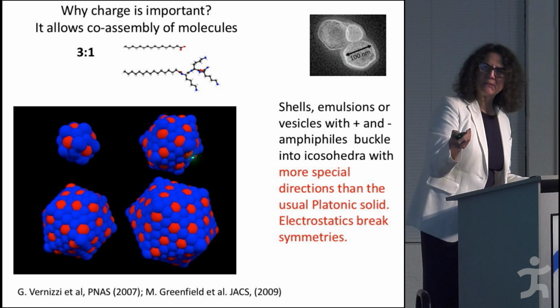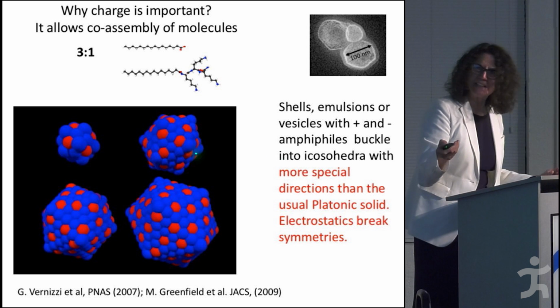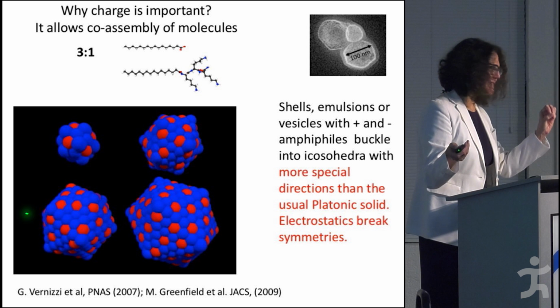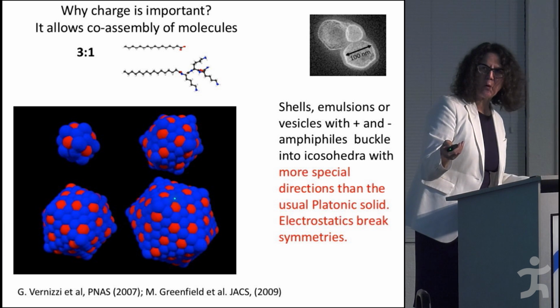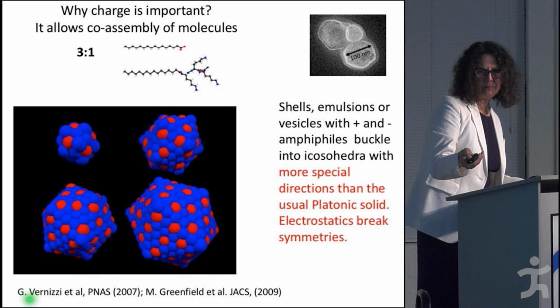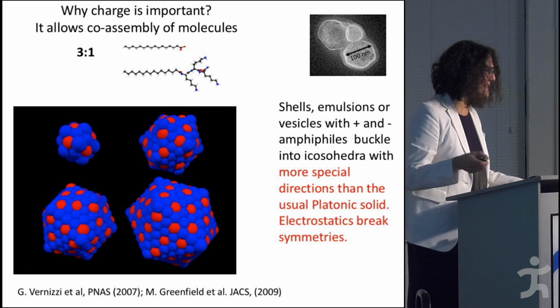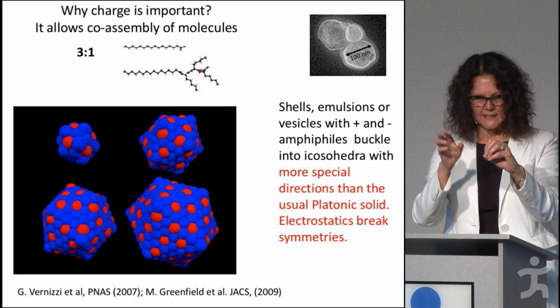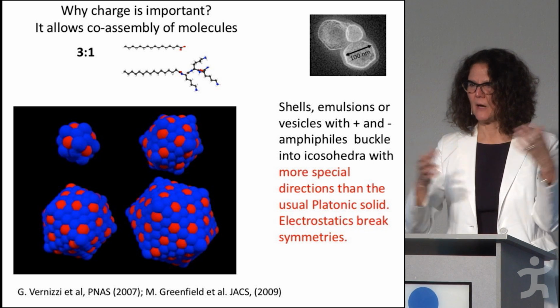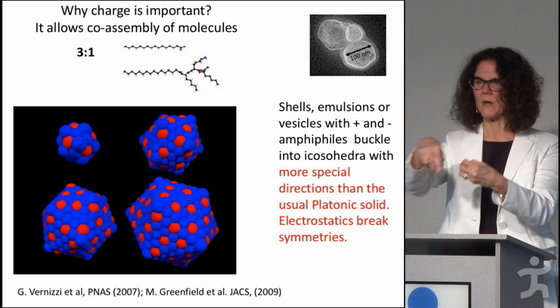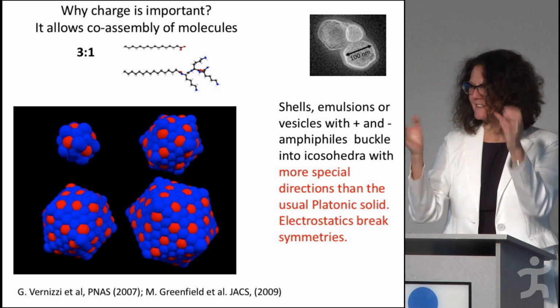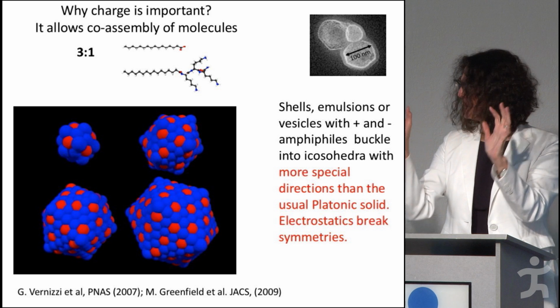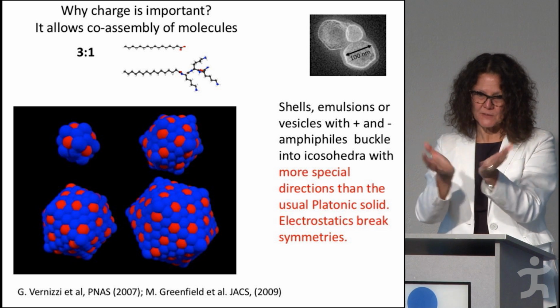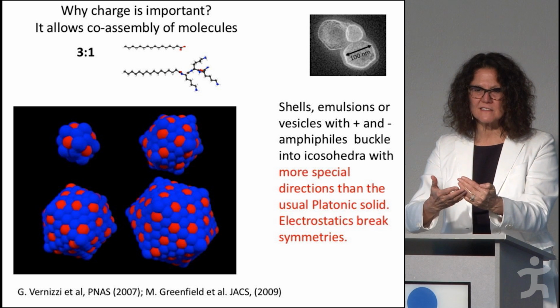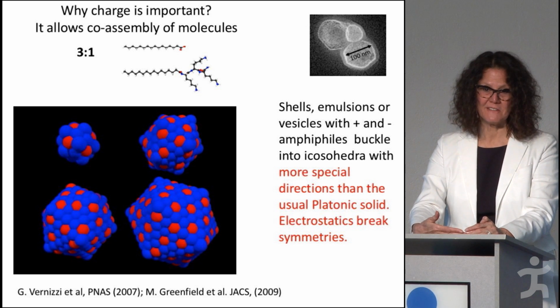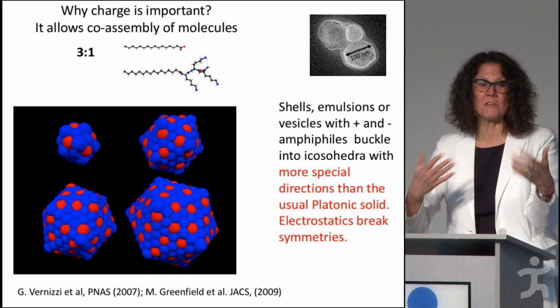But before I do that, I'm going to show you this example so you see the capability of electrostatics. These are objects that are the head groups 3 plus and then head groups minus 1. And so what we show here in this example, and this was a paper that won a Cozzarelli Prize by the National Academy, it's very interesting that if you take a sphere and you just put spheres that have positive and negative charges. Now, the interaction between charges is isotropic, it's 1/r in any direction, okay? The spheres that I chose have spherical shape too. So when we put them on the surface of the sphere, it happens that it has lower energy if you have something faceted, by the pure electrostatics. Okay, so by pure charge, they want to be faceted. Which is something very interesting.